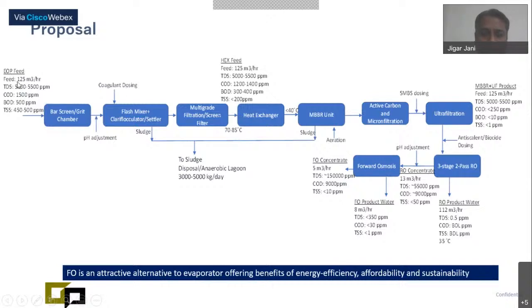As you can see, the total feed is 125 cubic meter per hour, with these TDS, COD, BOD characteristics. After some pH adjustment and coagulation dosing, it goes into the primary treatment. After primary treatment, and by reducing the temperature, it goes to the secondary treatment. Secondary treatment will mainly comprise a moving bed bioreactor, MBBR, followed by activated carbon and micron filtration, and then to have the finished product before it goes to the tertiary treatment, we are putting in the ultrafiltration system.